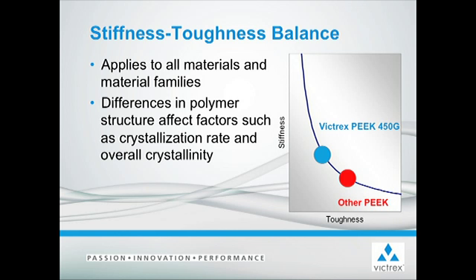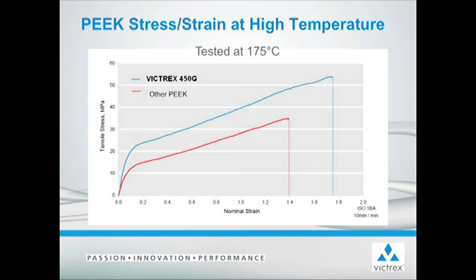The difference in PEEK materials can be referred to as a stiffness-toughness balance. In order to get stiffness, you have to compromise toughness, and vice versa. To increase toughness, you have to compromise stiffness. And this is due to differences in the polymer structure that affect factors such as the crystallization rate and overall crystallinity. This elevated temperature stress-strain curve also illustrates the stiffness-toughness trade-off. A higher ductility version of PEEK means it has lower crystallinity and lower tensile strength, especially at room temperature, but even more so at temperatures above the glass transition.